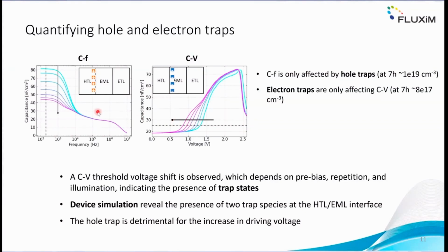And the other effect in this first 7 hours is also that the hole traps in the HTL at that interface increase from 0 to this value here. And these two assumptions were needed to describe these observations. So the device simulation really helped to understand what's going on.